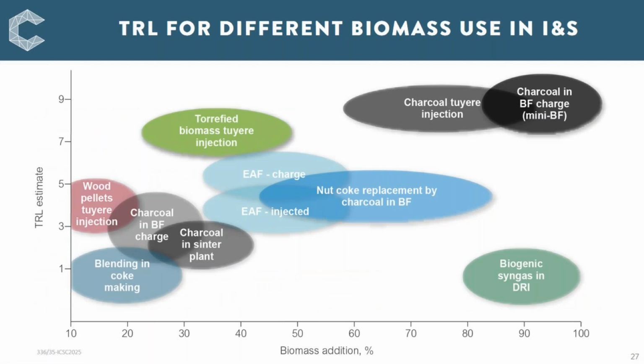So what we've tried to capture here is what the technology readiness level is for adding biomass and biomass products in different processes in iron and steel manufacturing, with the percent biomass addition at the bottom. And if I were to add charcoal onto here, we would be at the highest TRL and up to greater than 95% biomass addition. Well, certainly greater than 90% is already being done.